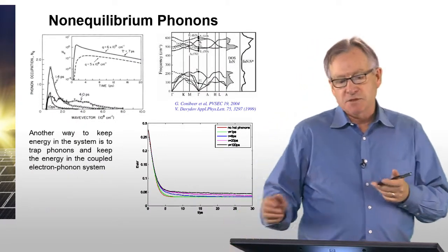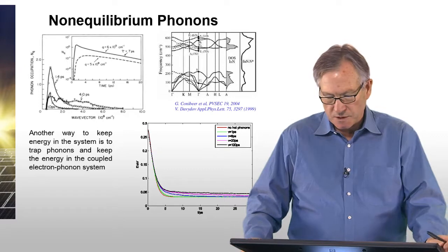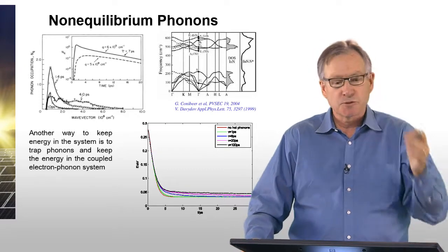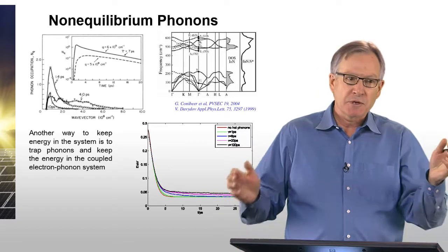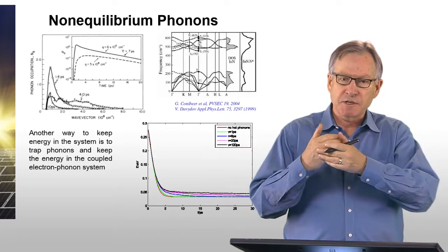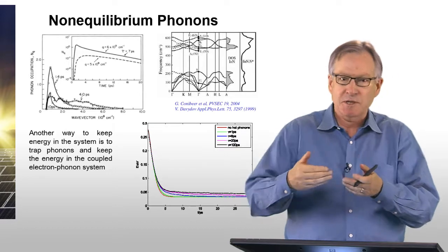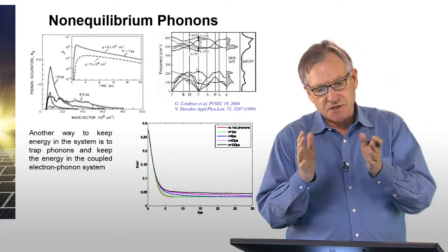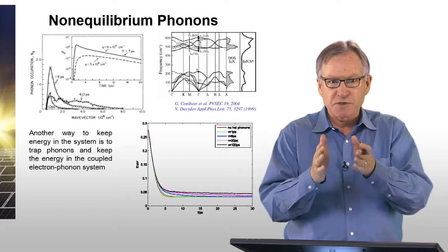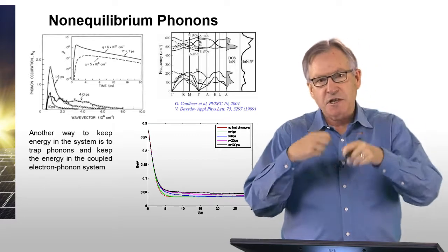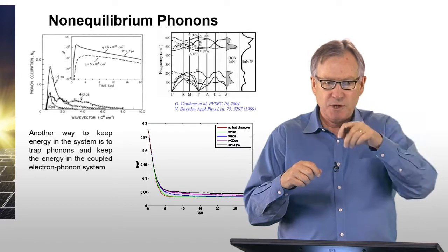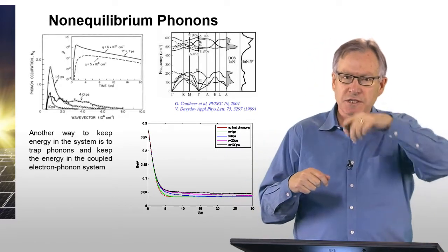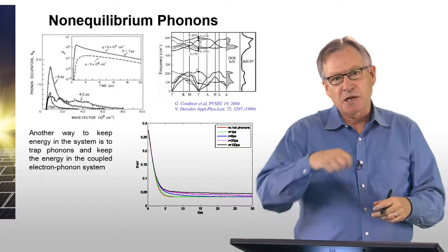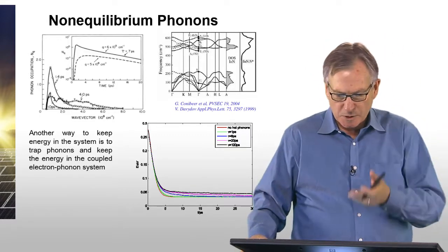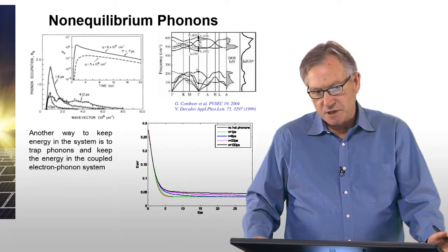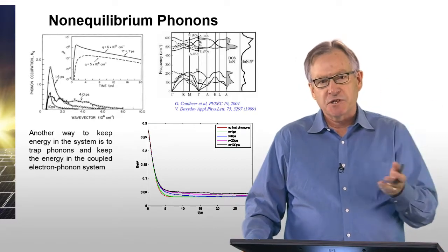Another idea that has been proposed primarily by the University of New South Wales group is that maybe we don't have to worry about the loss of energy of the electrons if we don't lose the energy of the phonons at the same time. In other words, if you keep the heat in the system, so if you could make a sort of thermal reservoir, the energy that's lost by the electrons would stay in the phonons. Those phonons could be reabsorbed by the electrons, and the electron-phonon system would stay at some elevated temperature. And this is the idea which is called non-equilibrium phonons, which is another approach to trying to keep that energy in the system.